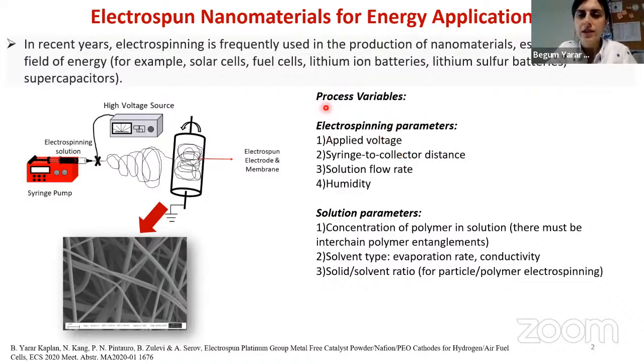We are dividing these process variables in two. One is electrospinning setup parameters, and the other one is solution parameters. Here, the applied voltage, the syringe to collector distance, solution flow rate, and the relative humidity of the system are really important to obtain a promising nanofiber mat or nanofiber structure.